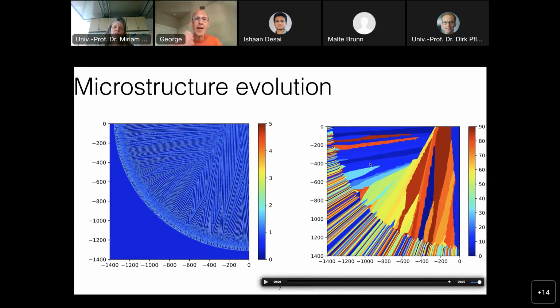So when we say microstructure prediction in these problems, what we mean is how big the grains are, what the dominant orientation is, how many grains are left, what the size distribution is. So microstructure prediction is basically statistics on the grains, their size, the crystallographic orientation, but it's also a random variable because it really depends on the seeds. So here, these colors that you see are basically some random substrate distribution. The metal in the